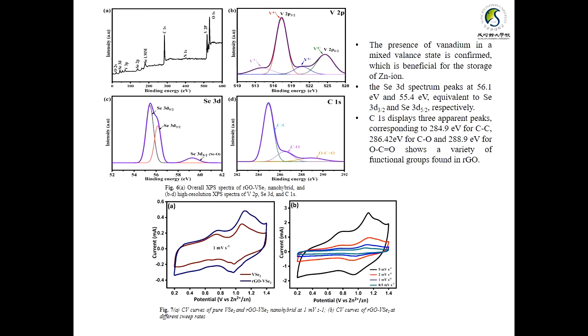The presence of vanadium in the mixed valence state is further confirmed with the existence of vanadium peaks of V3+ and V4+ states. The Se 3d spectrum peaks at 56 and 55 eV confirm the Se 3d pattern, and C1s displays three apparent peaks corresponding to 289 for C=C, C-O and O-C=O, showing a variety of functional groups found in the RGO. For this we have taken a cyclic voltammetric curve for pure VSe2 and the hybrid of reduced graphene oxide and vanadium diselenide at a fixed scan rate of 1 millivolt.